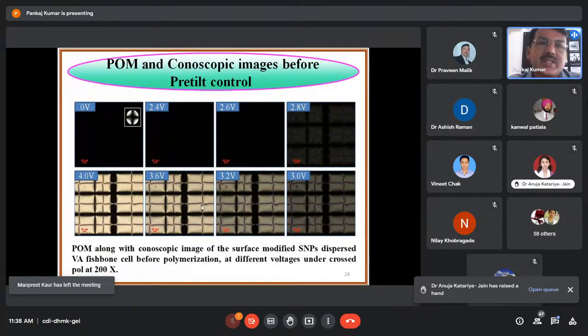And here you can see the POM and conoscopic images before pre-tilt control at 0 volt, 2.4 volt, 2.6 volt, 2.8 volt, 3.0 and up to 4.0 volt. So POM along with the conoscopic image, you can see here the conoscopic also, of the surface modified silicon nanoparticle dispersed vertical alignment in the fishbone cell before polymerization.